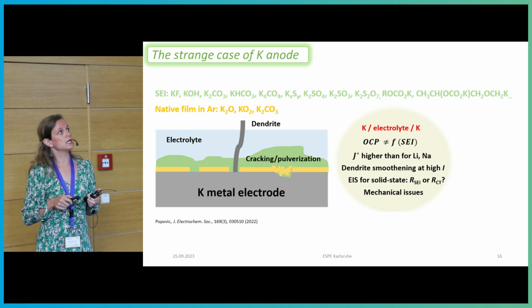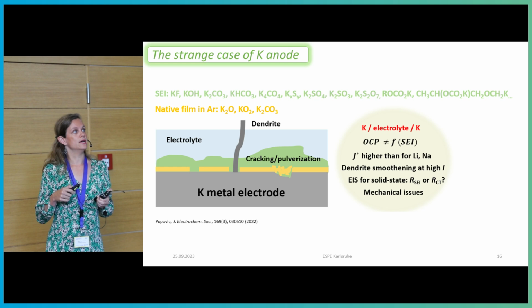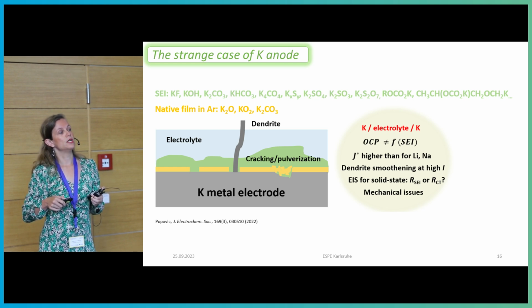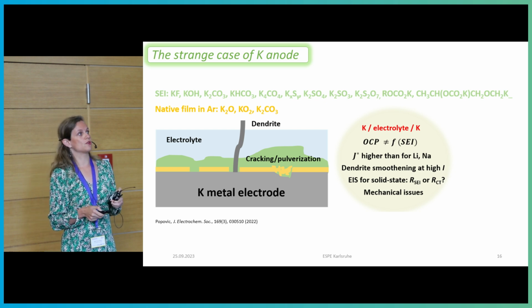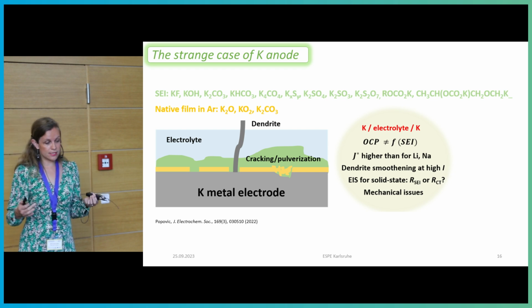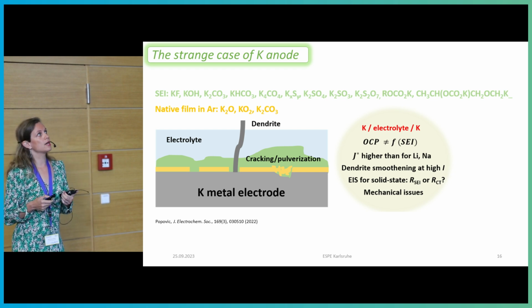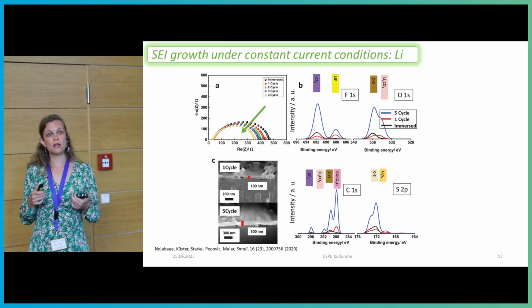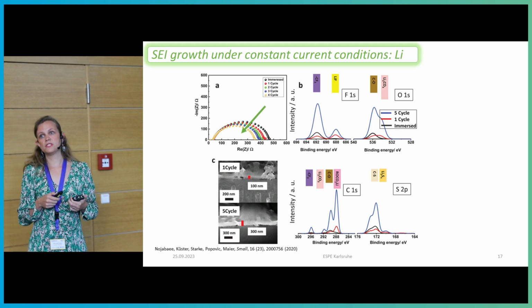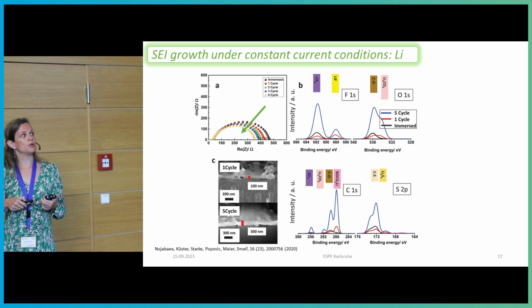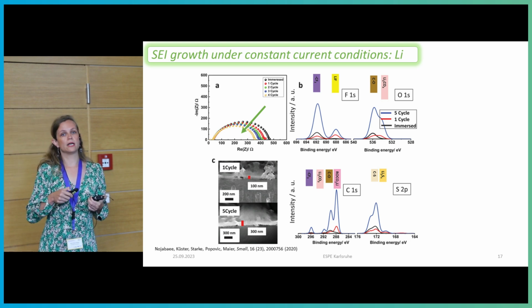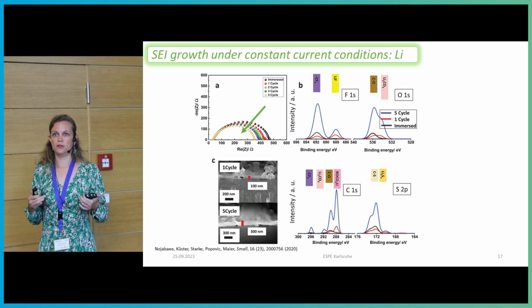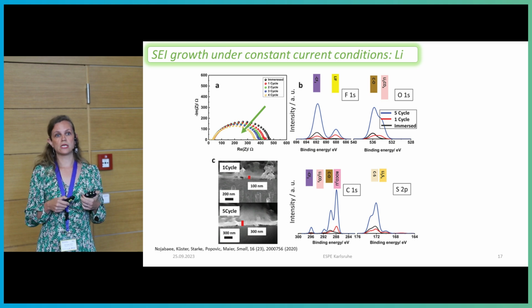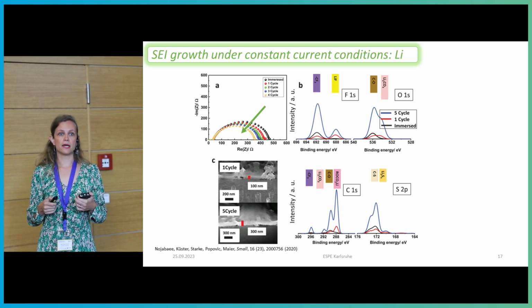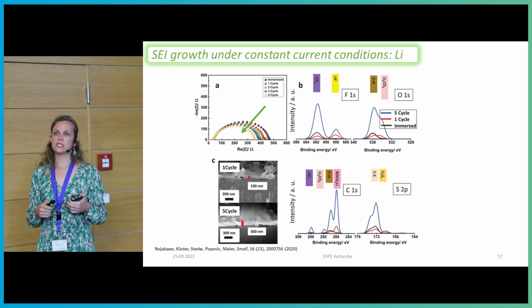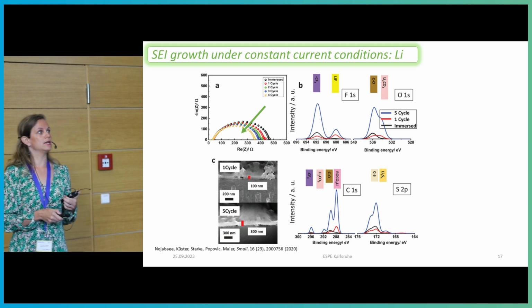And then what is interesting is to understand these mechanical properties of this SEI in time and in terms of solid state transport. I'll try to distinguish between the SEI and charge transfer resistance in this case. And how we started looking at these materials is actually by looking at the SEI growth under constant current conditions. And there we've seen something quite incredible happen. We've seen the resistance of the SEI dropping in time while the SEI was growing. And we could not actually distinguish this from the chemistry of it. So some years ago, we started looking into this and then decided to go 10 steps back and try to understand the OCV behavior before trying to understand the galvanostatic behavior. So there are quite many things to be done in this sense.